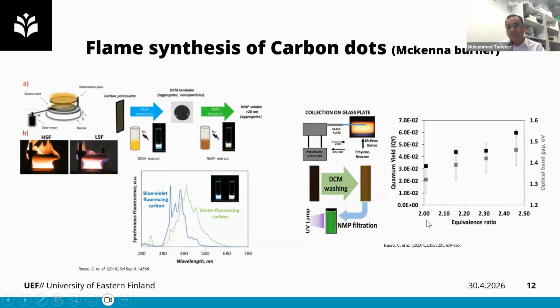So here you can see they have used equivalence ratio as a tuning parameter. They have used different equivalence ratios, and according to this change, they observed a band gap change in their nanostructures. When they increase the equivalence ratio, it will actually increase the particle size of the carbon dots. Particle size increment means that they are now shifting from blue to green, and then yellow dot region. It just means that they can be active in the UV region, UV visible region, and high visible region. So this is also an option, like by tuning the combustion condition, we can produce our material as per our need.